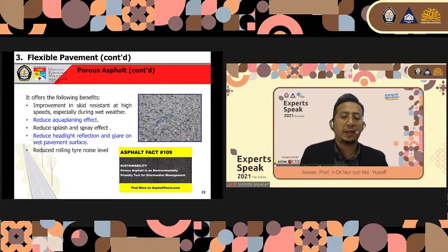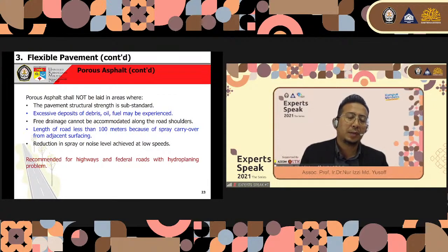And then this porous asphalt shouldn't be laid in areas where the pavement structure strength is substandard. Excessive deposits of debris, oil, fuel may be experienced. Normally, the biggest problem of using porous asphalt is the clogging problem. Whenever we use porous asphalt, we need regular maintenance. And then free drainage cannot be accommodated along the road shoulder. Length of road less than 100 meters is not suitable because of spray carry over from adjacent surfacing. Reduction in spray or noise level is not achieved at low speed. And then porous asphalt is recommended for highways and federal roads with hydroplaning problems.